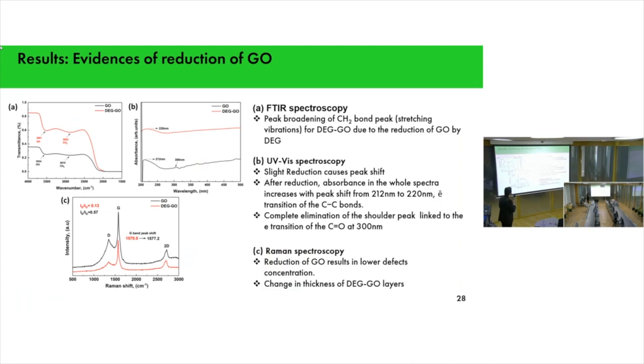So when you reduce the graphene oxide, you see there is a complete elimination of this shoulder peak. Moreover, if you go to the Raman spectroscopy, you see there is a G band and a D band. G band represents the sp2 structure, whereas D band represents the defect concentration. So when you take the ID to IG ratio, you see there is a decrease in the ratio to 0.13 from 0.57 when you reduce your graphene oxide filler.